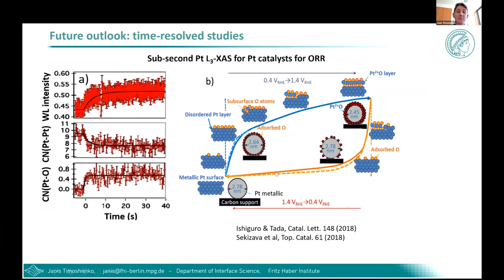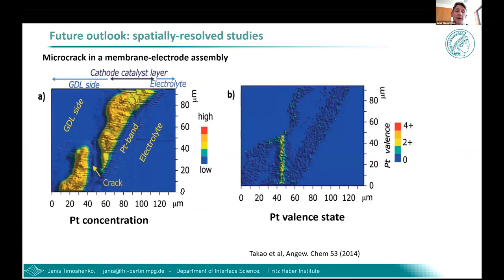In this particular case, we can try to single out the contributions of processes like chemisorption of certain adsorbates, oxidation of the catalyst surface, or restructuring, meaning changes in the geometric structure of our catalyst nanoparticles. And clearly the ability to collect spectra quickly is also very beneficial for spatially resolved studies. Here we can use a focused X-ray beam to scan over large areas of our sample and collect X-ray absorption spectra in each pixel, each point of our sample. This allows us to investigate the importance of heterogeneities in our catalytic system, for example the role of cracks in our electrodes. And it can be linked, using X-ray absorption spectra analysis, to a locally enhanced platinum oxidation state, which again may have important consequences for explaining the catalytic performance of the overall electrocatalytic system.